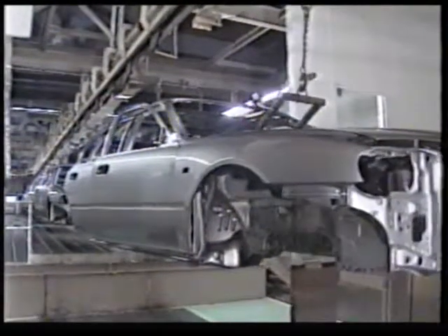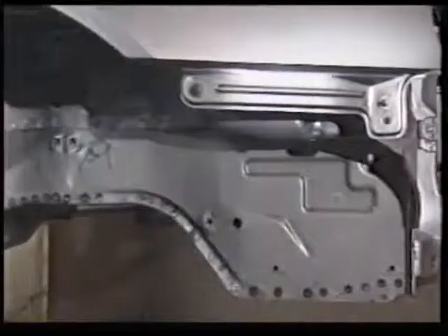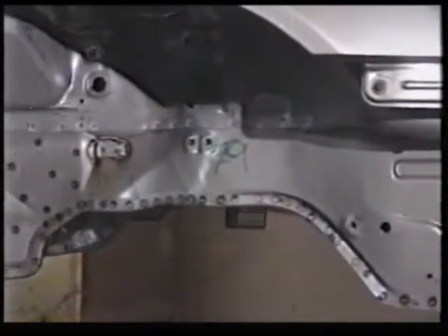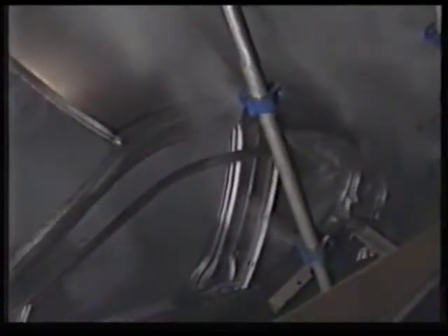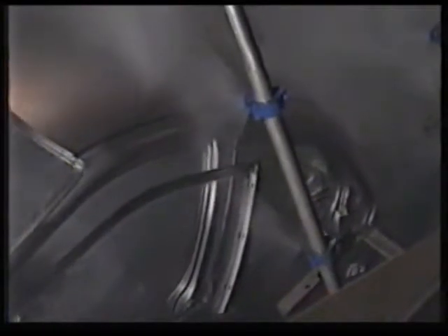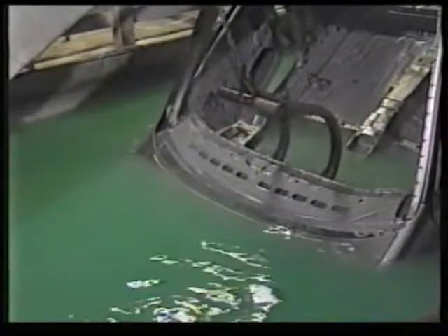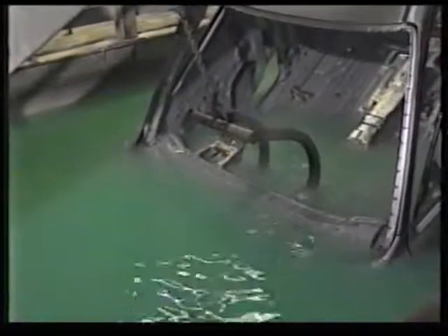After 331 panels have been given 4,500 spot welds, the body in white, as the industry romantically calls its creation, is given a thorough clean, including a hot bath in an alkaline mix of complexing agents and surfactants, followed by a cold rinse before treatment with a colloidal solution of titanium phosphate. The body in white emerges covered in minute crystals, which are going to act as nuclei for the climax of the process, full immersion in a tank containing zinc, manganese and nickel phosphate, and an oxidizing agent.